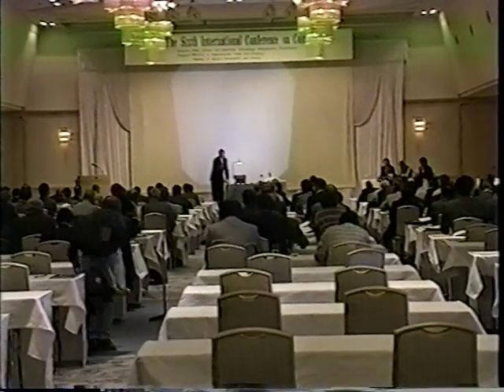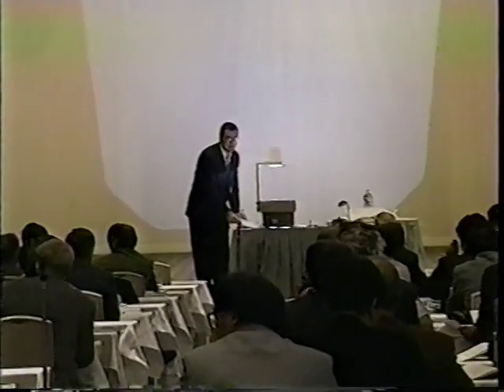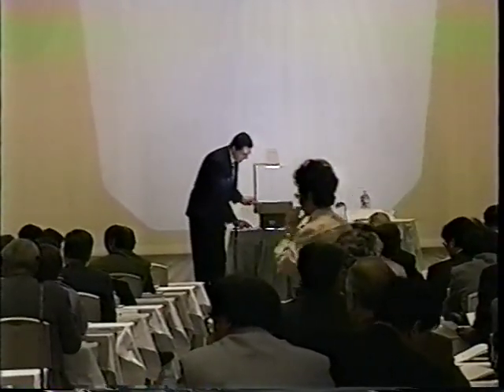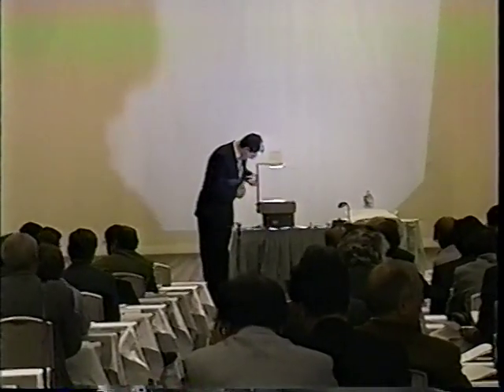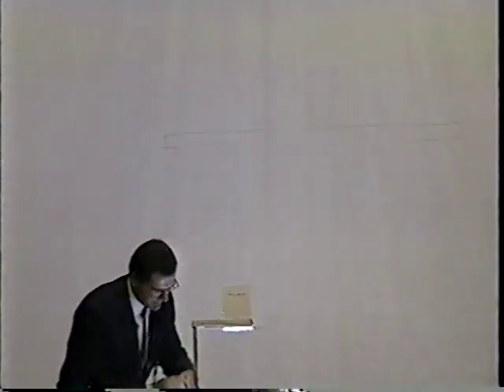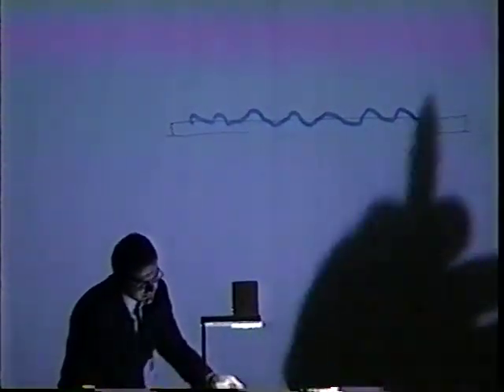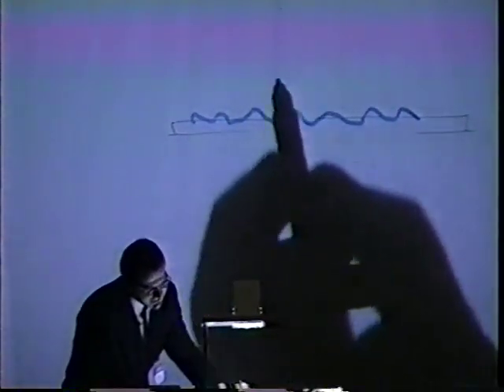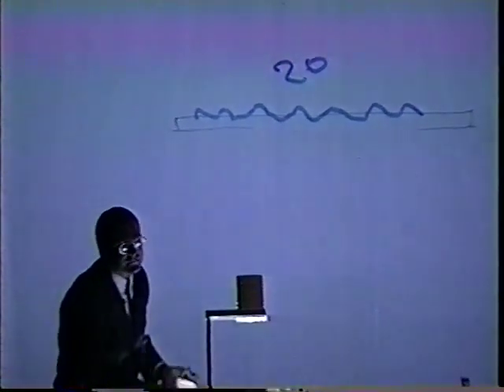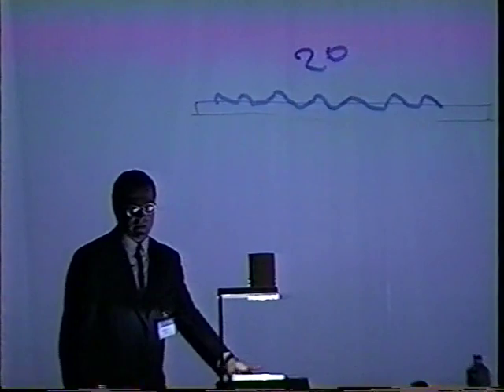Such kind of transverse undulations between the two ends of the sheet, in a number of about 20. This is a systematic thing we always see in our sample. It means if one looks at the lateral sides of the sample, one observes a situation like this. It's not precise, of course, but this number is about 20 undulations along the length. This is the only mechanical fact that we can note.